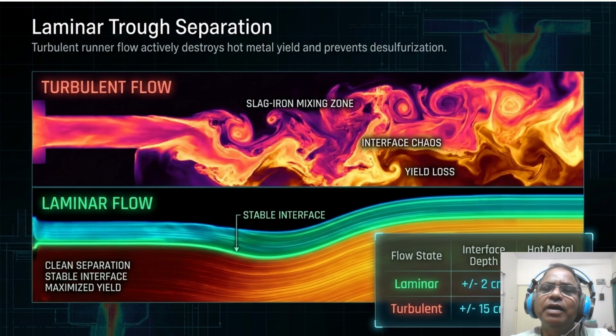Now look at the laminar flow. You see a stable interface with a clean separation. The data table tells the whole story. Laminar flow has a plus or minus 2 centimeter interface depth and only 0.1% yield loss. Turbulent flow has a plus or minus 15 centimeter depth and kills your yield by over 2.5%.